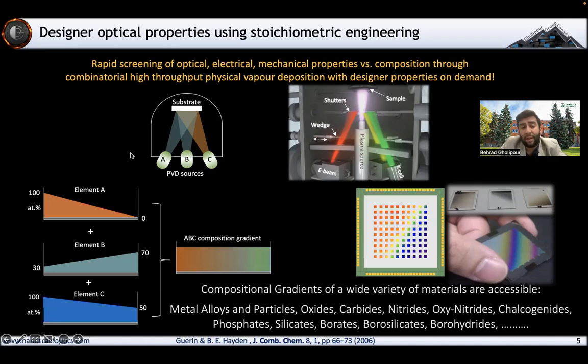You can take any sort of PVD chamber. This is a physical vapor deposition chamber that can be made up of electron beam sources, evaporation sources, plasma sources, so sputtering, evaporation, or various other PVD techniques. All of them you can use this with. And what we do is we put a little wedge between our sample and our sources. And by controlling the position of this wedge, we can create very controlled thickness gradients of various elements that we're making as part of that alloy that we're trying to deposit.